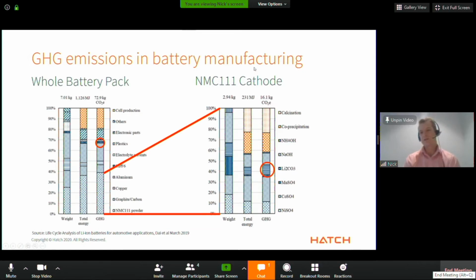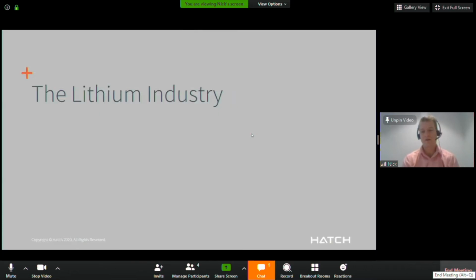And this second graph here is expanding that section of the graph further and looking at its constituents. So you see a couple of things. I've highlighted the different aspects associated with the lithium. So there's a tiny contribution here associated with the lithium hexafluorophosphate, which is the electrolyte within a battery pack. And then there's the lithium carbonate contribution to the overall cathode. So the real key point here in this section is none of this happens without lithium. Lithium's a key enabler, but it's not a significant contribution to the overall greenhouse gas intensity of battery manufacturing.